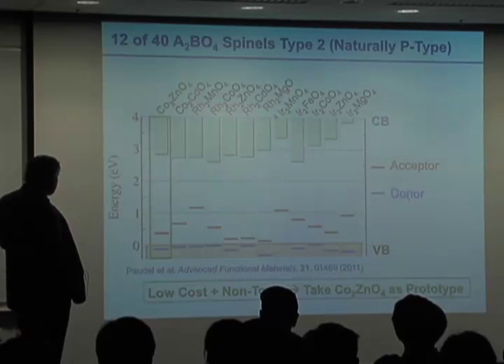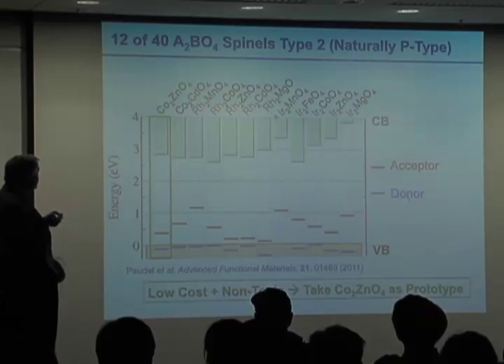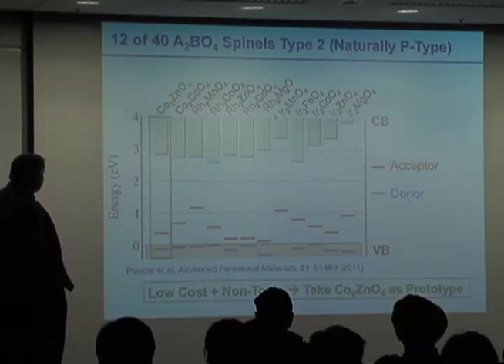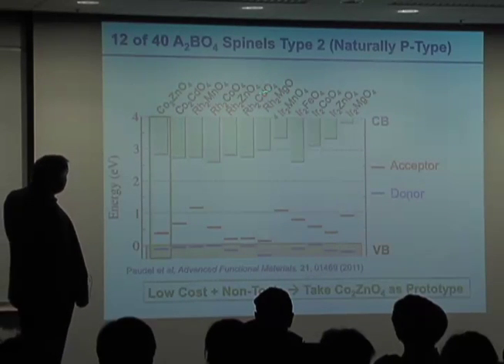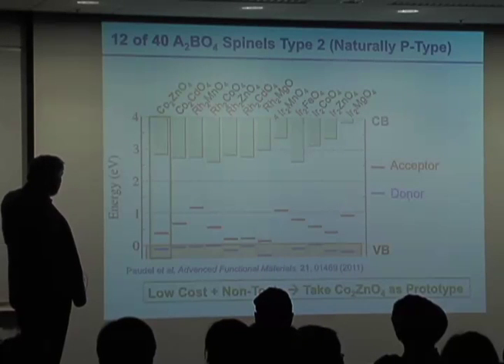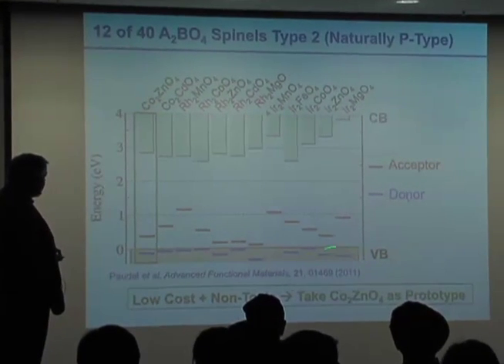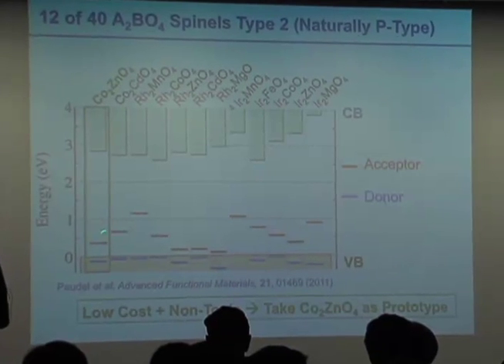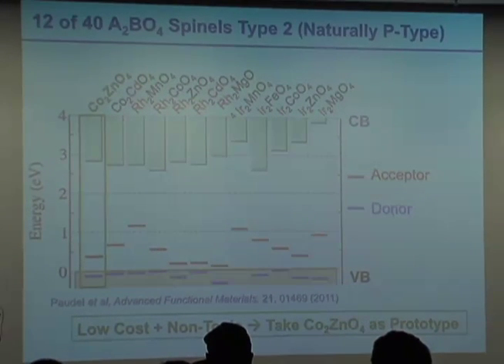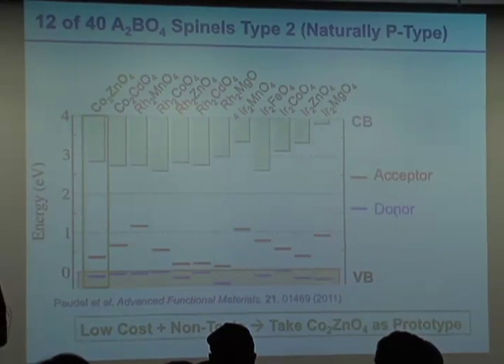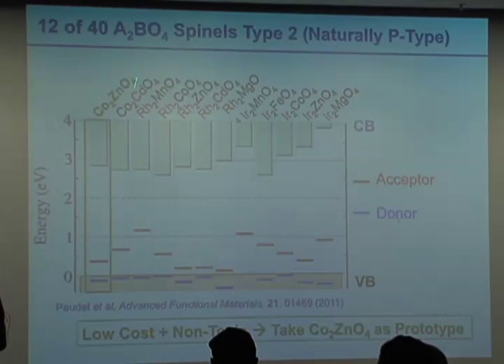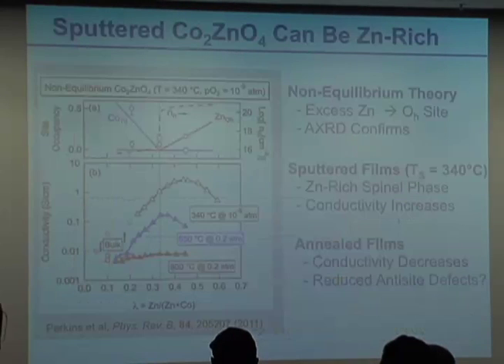And so we've actually looked at a set of spinels, and it turns out of the 40 spinels we looked at theoretically, 12 of these are naturally p-type, where the donor level is buried in the valence band and the hole producing acceptor level is actually in the gap. And when we look at these systems, we take a look and say, from a toxicity and low cost standpoint, cobalt and zinc seems like a really good prototype to get started with. So we've actually started to do some very detailed studies on this.